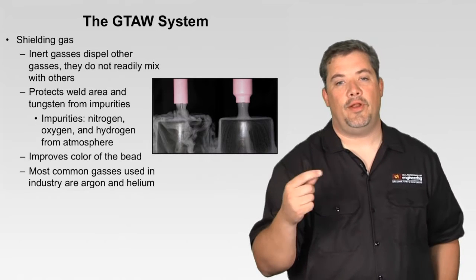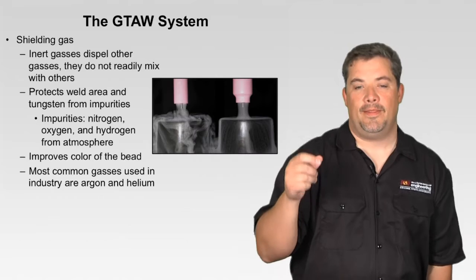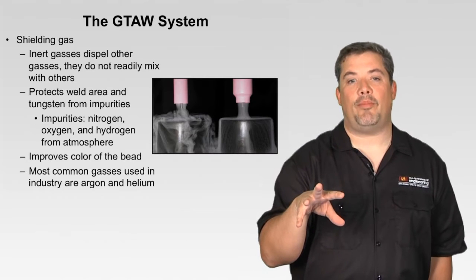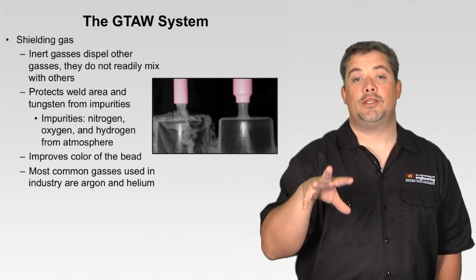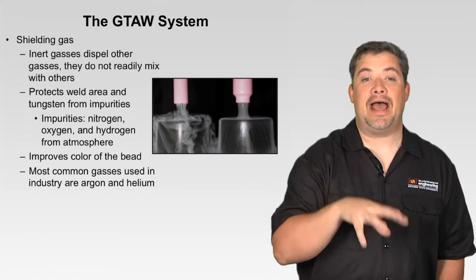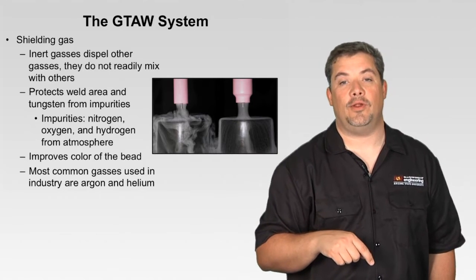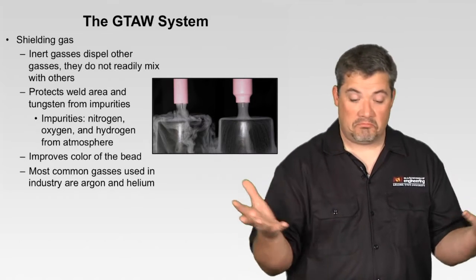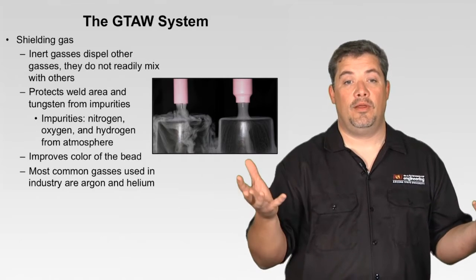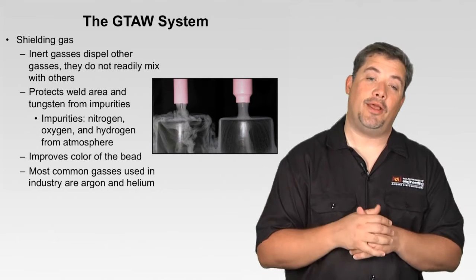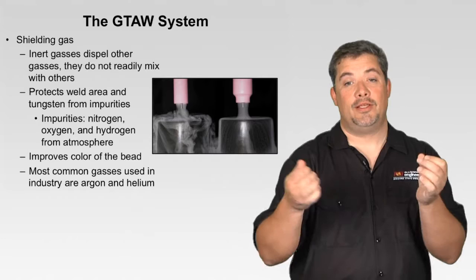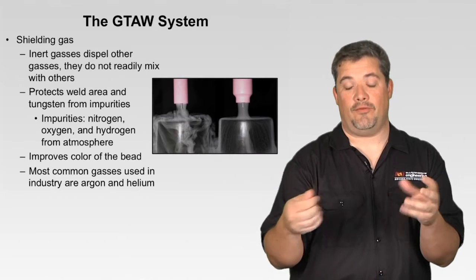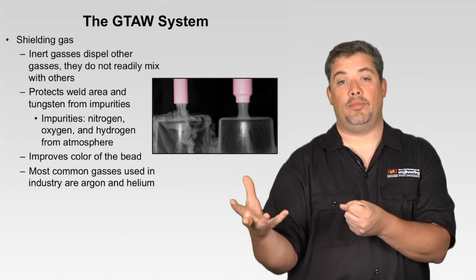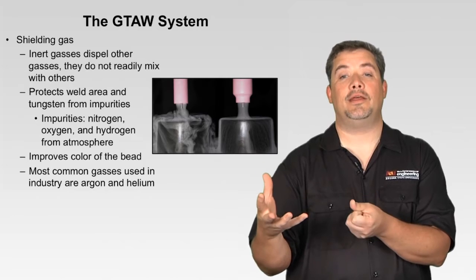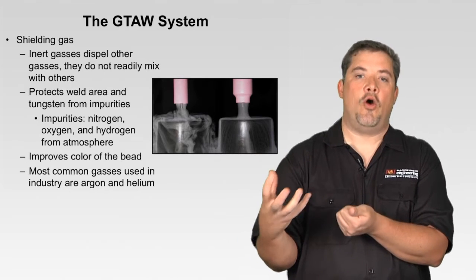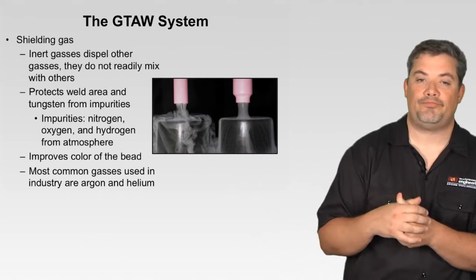So the improvement of the color of the bead really means that the argon shielded that part long enough to cool so that that surface did not get oxidized from the atmosphere. If I'm in an argon bubble, welds are going to be shiny clean. But typically we're not welding in an argon bubble, we're out in a shop, so we need to make sure we have good adequate gas coverage so that as we move along, that weld behind us isn't so hot that it gets overly oxidized on the surface.